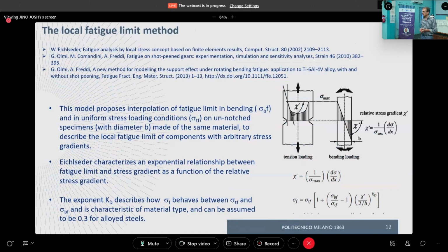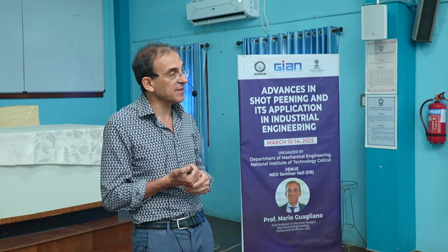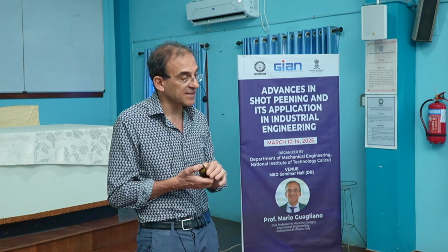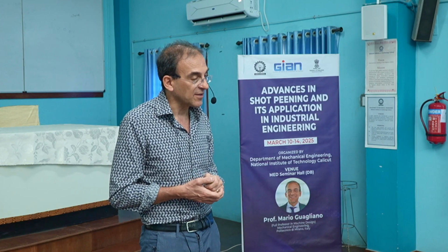The method was developed initially in Germany. Eichlseder and others developed the method. And it's not only for shot peening, of course, this is for surface hardened materials. And they say that due to the application of our surface hardening process, we can get an improvement of the fatigue limit that is a function also of the geometry of the notch, and in particular of the stress gradient caused by the notch.